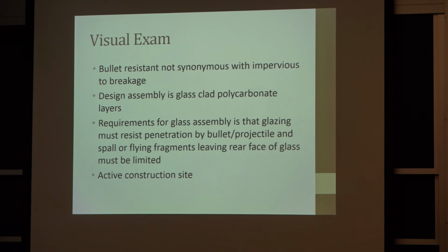All right. Professor Eager showed you the bulletproof glass he had, and it has multiple layers. The one he showed you had about 5 or 6 different layers stacked up. So just because you're buying bulletproof glass doesn't mean that you can't get scratches and breaks in it. The way they do the bulletproof glass is they have a glass-clad polycarbonate, and that allows the glass to absorb more energy. The requirement for the glass assembly is that the glazing must resist penetration by a projectile, and you don't have any glass fragments flying. So if you did shoot a projectile at the glass and it stopped the bullet and you don't have shards everywhere, that would be a glass that operates as intended. Just because you had a nick on the glass doesn't mean that the glass was manufactured improperly.